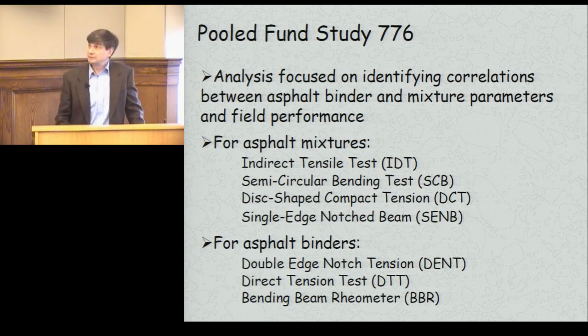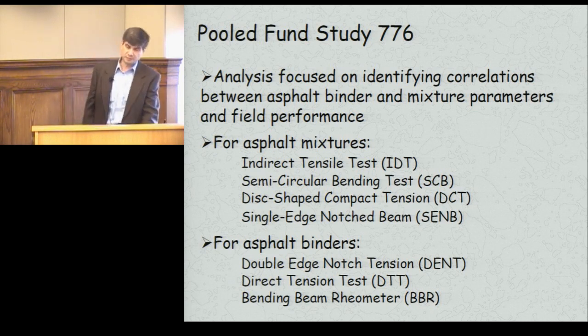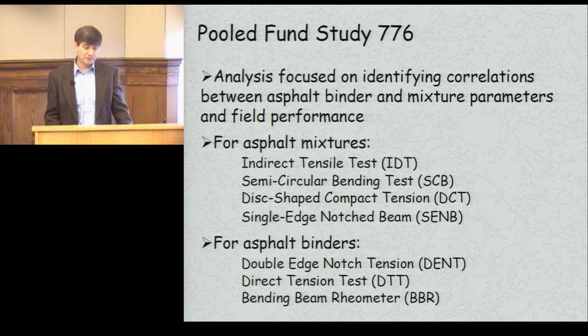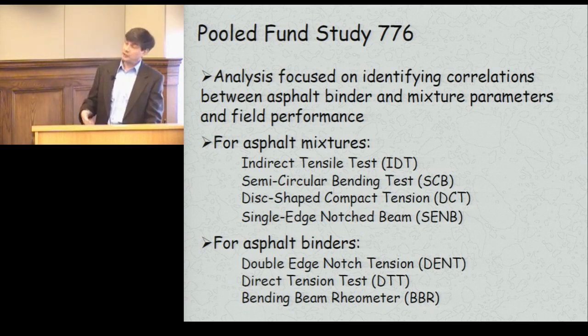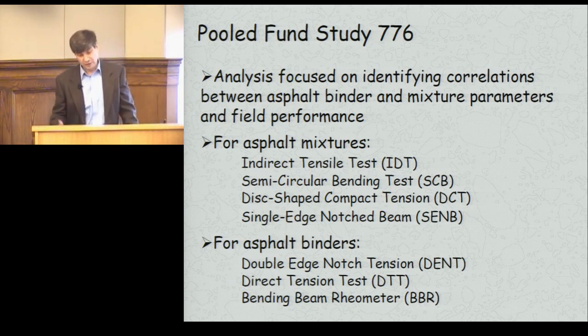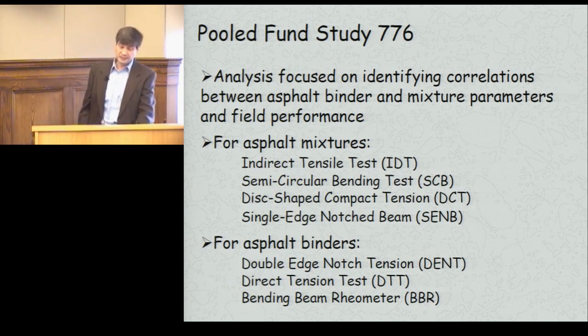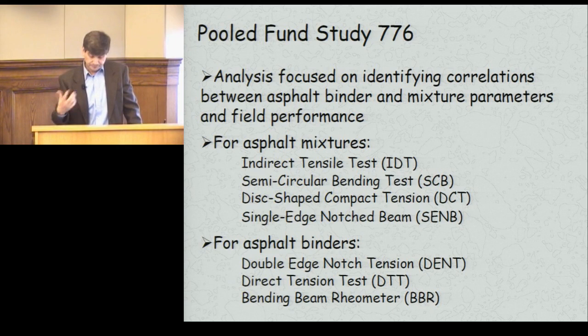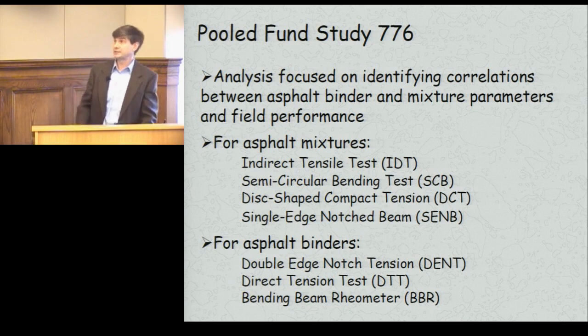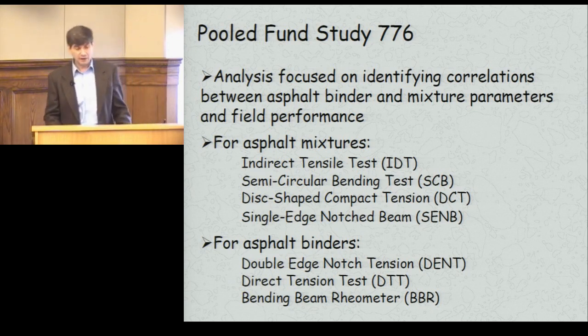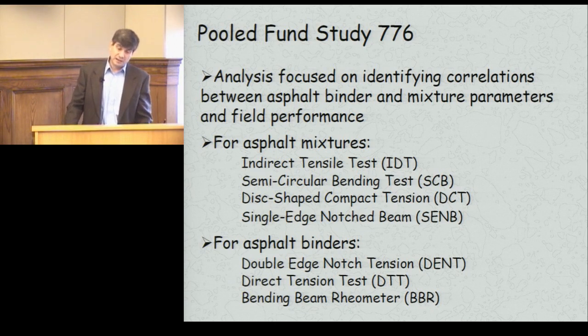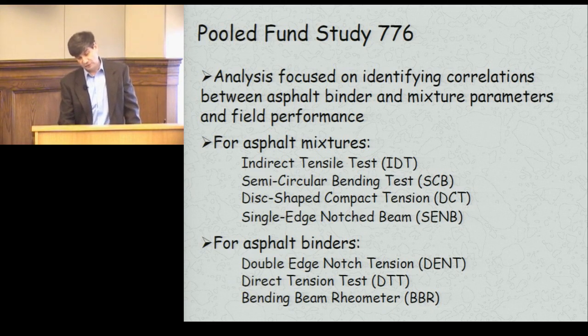So anyway, we tested a set of mixtures using 4 different types of test procedures. Some of them, 3 of them, were fracture-based tests. The IDT, indirect tensile test, was actually a strength test, and for asphalt binders we also used 3 different strength tests. The testing was done on materials prepared in the lab, but we also took cores from pavements selected by our sponsors, various states, that had good and bad pavement performance, and we correlated the results to the performance.